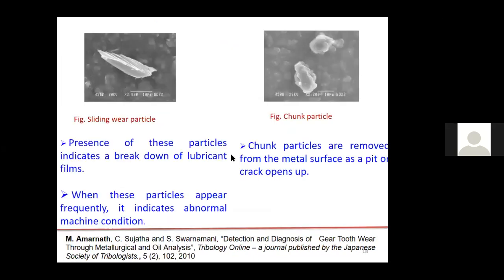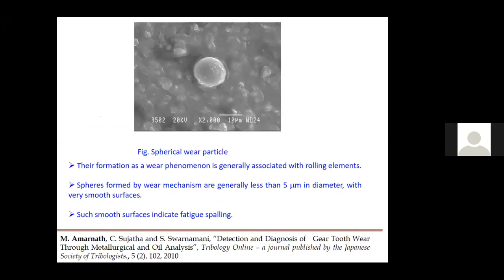There are various types of particle morphology like sliding wear particles, chunk particles, fatigue wear particles, spherical particles, etc. Each particle morphology will give the details of wear propagation. For example, sliding wear particles will give the details of breakdown of the lubricant film, and chunk particles will give the details of pit propagation. When a pit opens up, this type of chunk particle will be observed in lubricant samples. Spherical wear particles are related to wear of rolling elements. These are some examples of wear particles developed in a gearbox. The details are available online in this reference, so for further details you can refer to this.